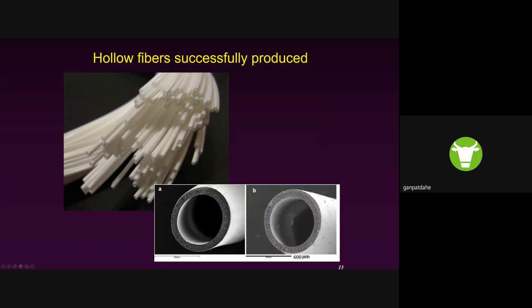And these are some SEM micrographs of the hollow fiber. You can see these structures, which are called macrovoids. They form when the precipitation is really fast and when the mass transport happens through convective mass transport rather than diffusion. This is very typical, a fingerlike structure of cavities called macrovoids.